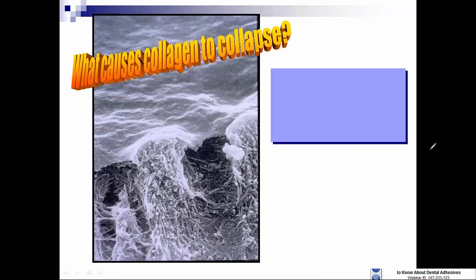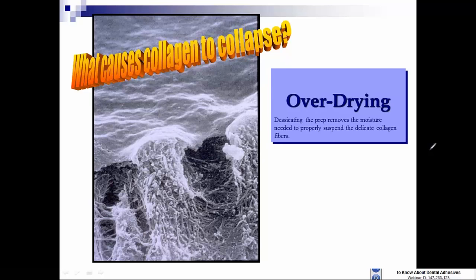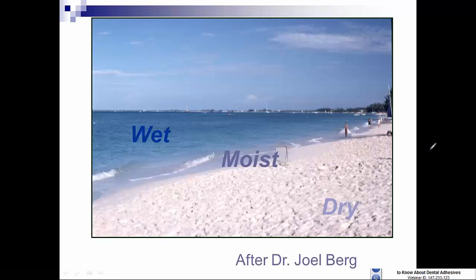Now, what causes collagen to collapse? And in this micrograph, we're not looking at the smear layer, we're looking at those collagen fibrils which have been dried and caused to collapse to create a barrier, preventing the resin monomers from penetration. So desiccating the prep and removing that surface moisture that keeps the collagen separated and moist causes this collagen collapse. Now, there's been a confusion about what is moist or wet bonding.